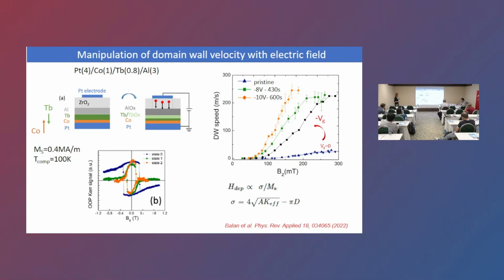So how do you explain this? What we think is that by gating we start oxidizing partially the terbium layer, and therefore we expect the magnetization to increase. We see that the anisotropy increases, therefore the depinning field decreases, and then we can recover these high speeds. So the idea is that we are passing from a system in which we have domain walls in the creep regime to domain walls in the flow regime. We have this huge variation of the domain wall velocity.